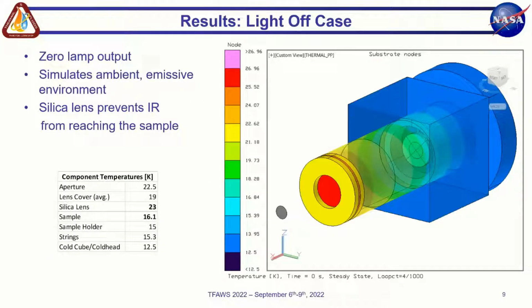Okay, so now I'm going to start with the light off case because this is the most straightforward one. This included, as the name implies, 0 lamp output and simulates an ambient emissive environment in which one inner wall of the chamber was set to ambient temperature. This case was run to ensure that no infrared reaches the sample downstream. And these results show that the silica lens was effective in preventing infrared from reaching the sample, because the highest temperature reached with the light off was 23 Kelvin, and the sample remained at 16 Kelvin.